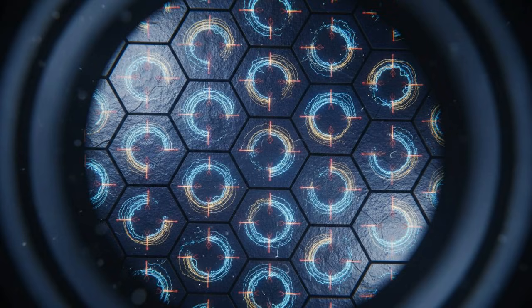Researchers found that at certain alignments, twisted graphene exhibits orbital ferromagnetism. In a standard magnet, like the one on your fridge, magnetism comes from the spin of electrons. In twisted graphene, the magnetism comes from the orbital motion of electrons swirling around those moire cells. They create tiny current loops, effectively turning the material into a grid of microscopic electromagnets. This leads to the Quantum Anomalous Hall Effect, where electricity flows along the edges of the material with zero resistance and zero magnetic field. This is a crucial property for developing low-power quantum electronics.